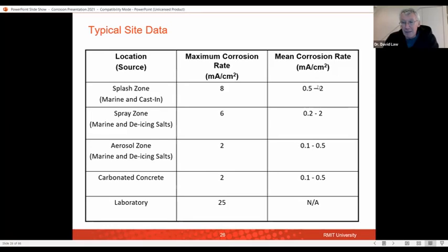And when we then convert those to our mean corrosion rates, if we multiply that by a number which is approximately 10 that comes out of that Faraday equation, that will tell us how many microns of steel we lose per year. So typically, we can be losing around 20 microns of steel a year in our splash zone. In our carbonated concrete, it might be down at only, say, 1 micron a year to 5 microns a year. So that's the difference between our pitting and our uniform as well. You can see that chloride corrosion goes a lot faster than our carbonated corrosion. I can say that on site, I've actually had values up here that not 20, but actually 80 microns a year or 90 microns a year. We have seen that on occasions, but generally they're in these zones for the typical site data.